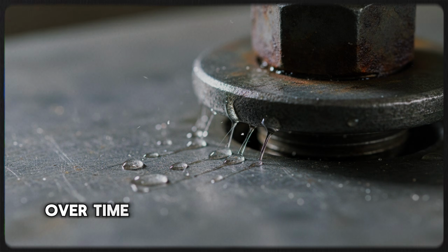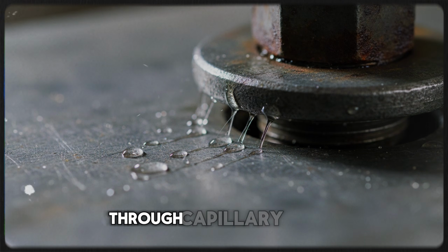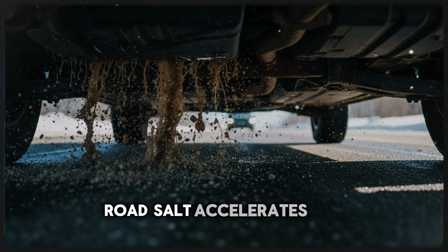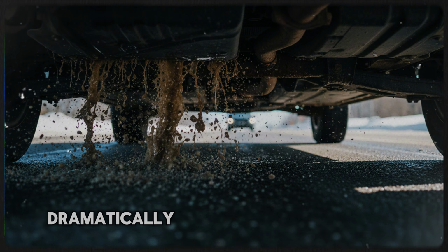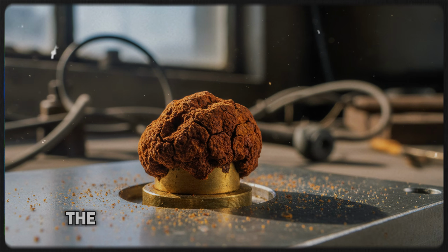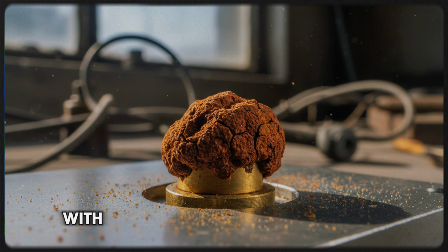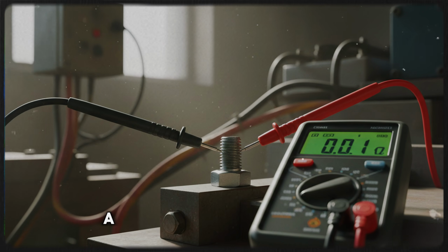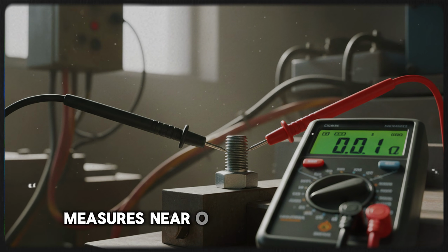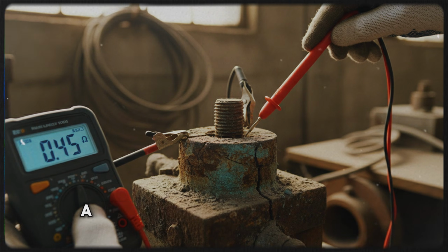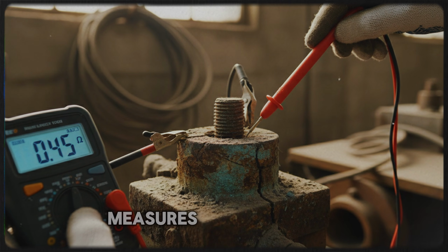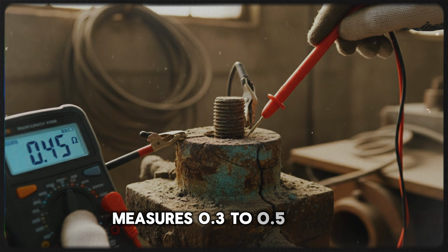Over time, moisture wicks under the bolt head through capillary action. Road salt accelerates the electrochemical reaction dramatically in winter driving regions. The iron oxide layer grows thicker with every seasonal moisture cycle. A fresh ground connection measures near 0 ohms of resistance. A moderately corroded ground connection measures 0.3 to 0.5 ohms.